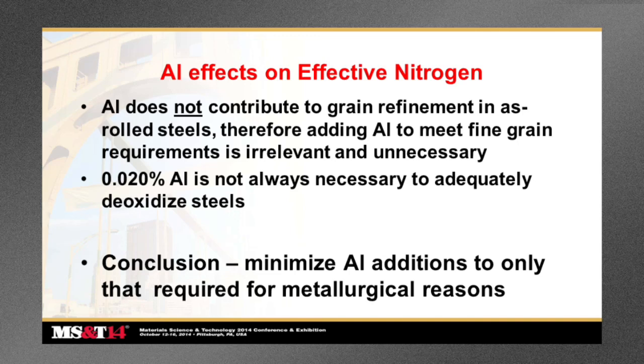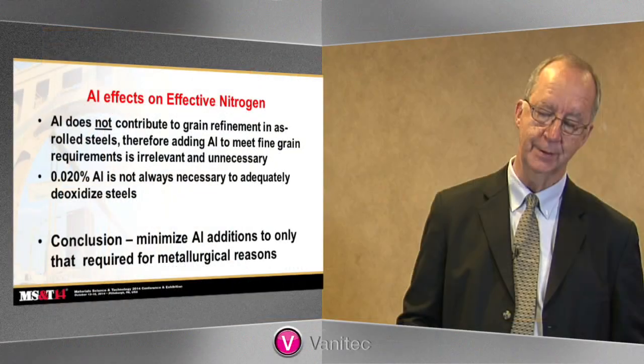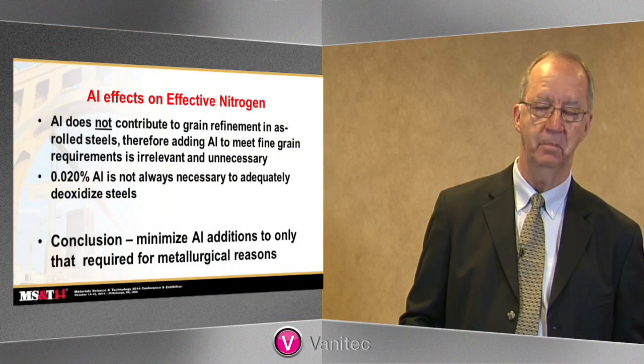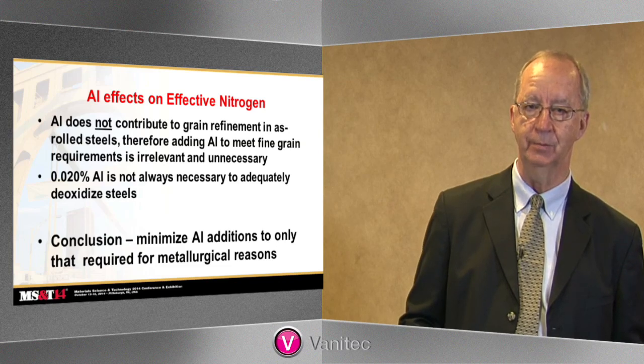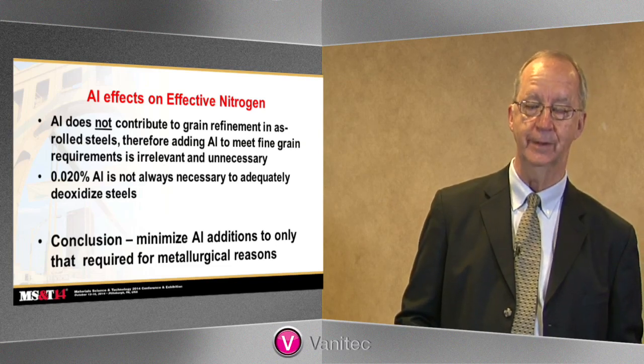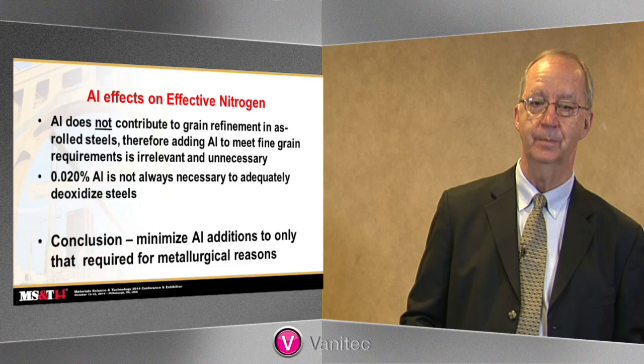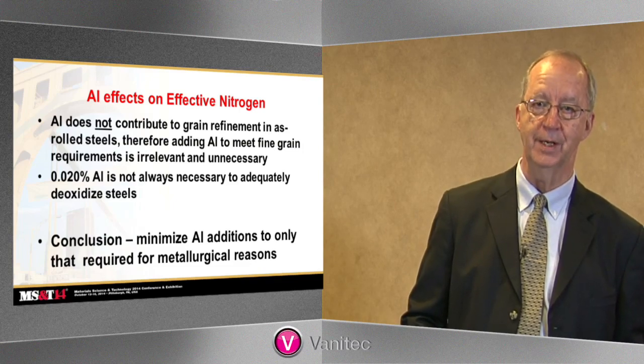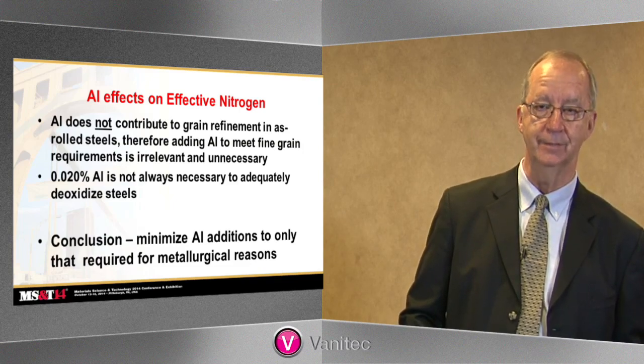So the conclusion is that if you're using a vanadium nitrogen system and you want to be able to achieve strengths as predicted by this model that we are proposing, you should minimize the aluminum additions so that you're only using the amount that's required for metallurgical reasons. And this includes, of course, primarily deoxidation, because grain refinement in an as-rolled ferrite pearlite structure is mostly controlled by the process conditions, not the addition of aluminum.